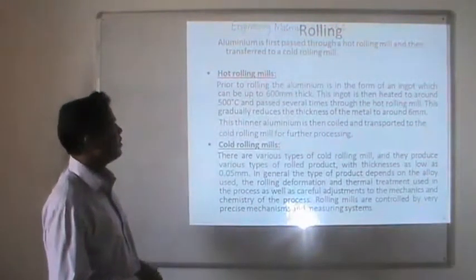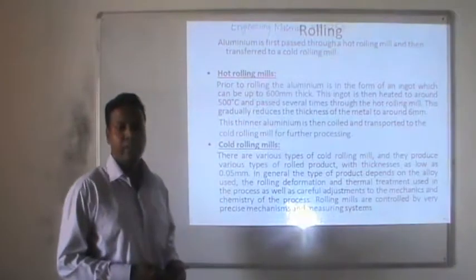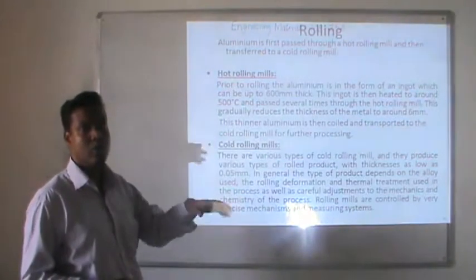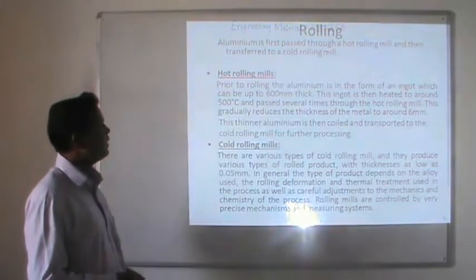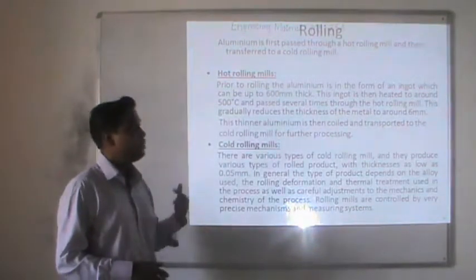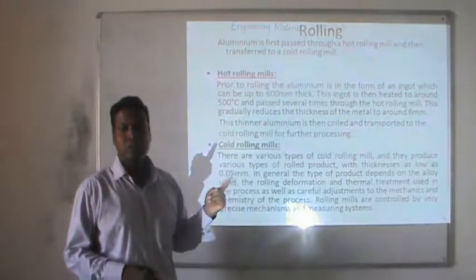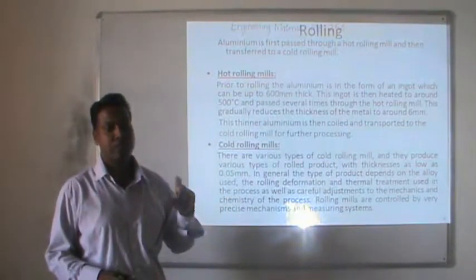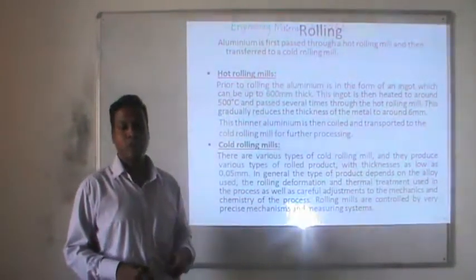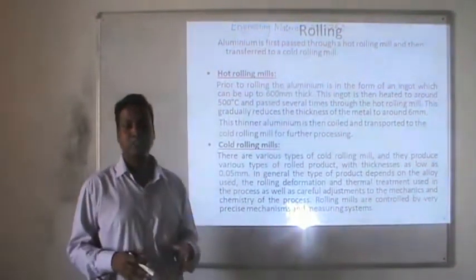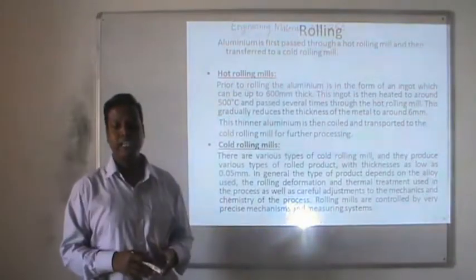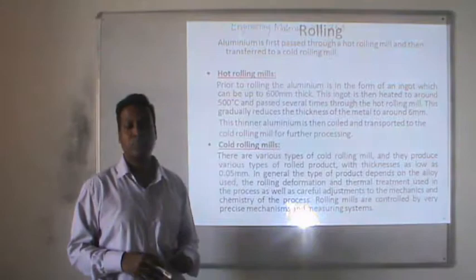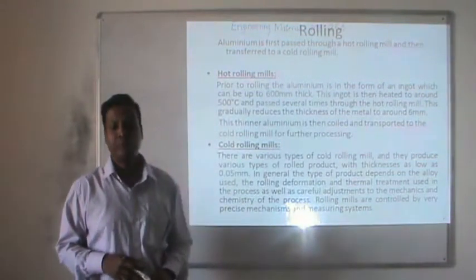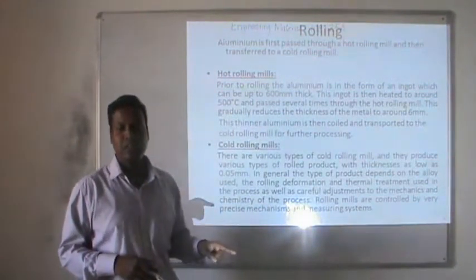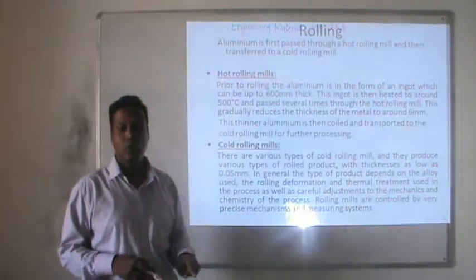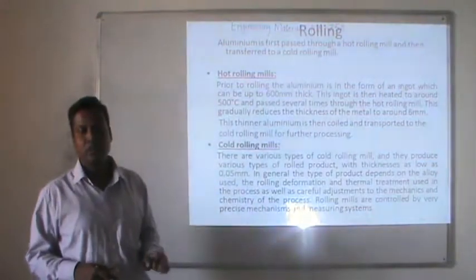This is the rolling process. The aluminium first passes through hot rolling mills and is then transferred to cold milling for finishing. Prior to rolling, the aluminium is in the form of ingots which can be up to 600 millimeters thick. The ingot is then heated to around 500 degrees centigrade and passes several times through the hot rolling mills. This gradually reduces the thickness of the metal to around 6 millimeters. The thinner aluminium is then coiled and transferred to the cold rolling mill for further processing.